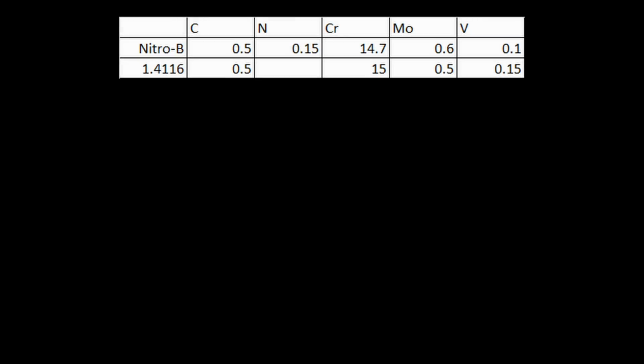So we're gonna move on to Nitro-B, which is a steel made by Buderus. This steel isn't used in that many knives. It's pretty new, so it's probably seeing some use under different names. And this is identical to a very common German stainless, which goes under some really boring, hard to remember names. So 1.4116 or X50CrMoV15. It's 50 points of carbon, 15 chrome, a little bit of moly and vanadium. And Nitro-B takes that same steel but adds about 0.1 or 0.15 nitrogen to it.